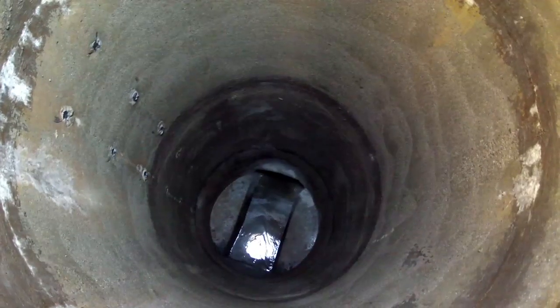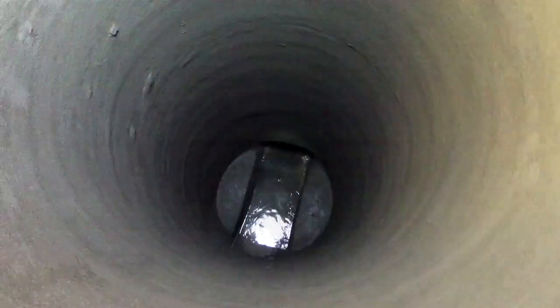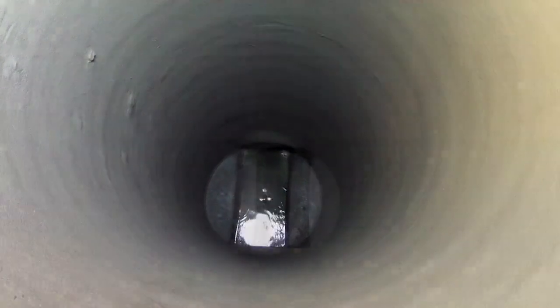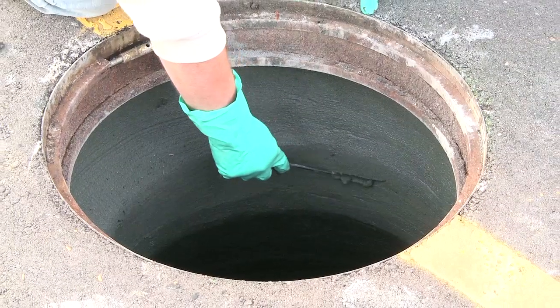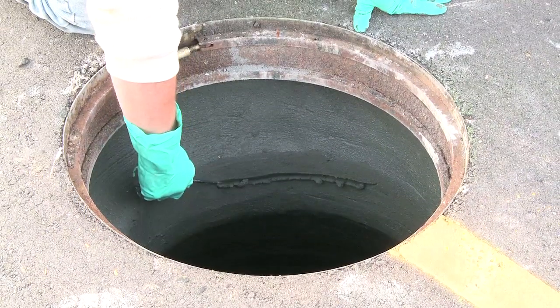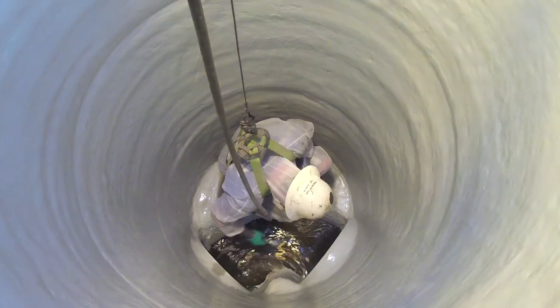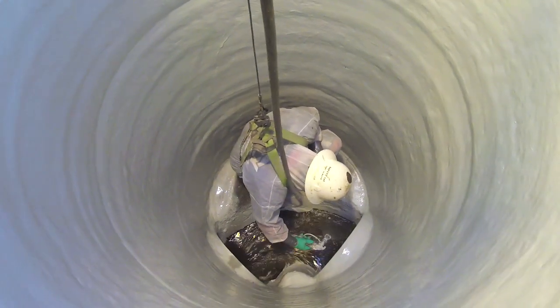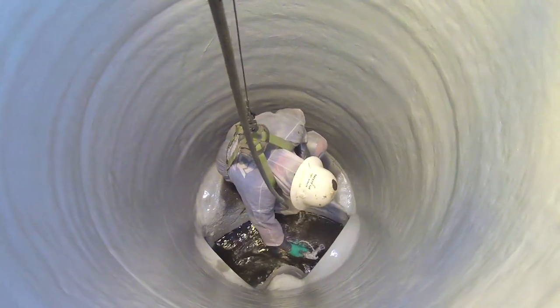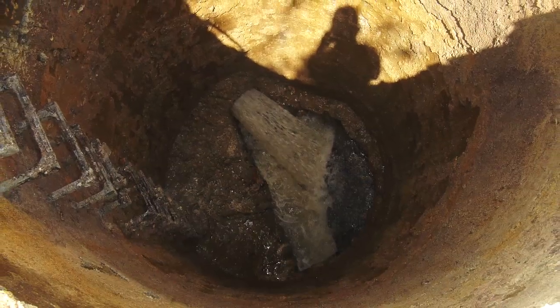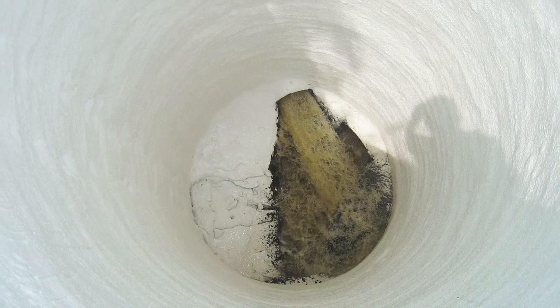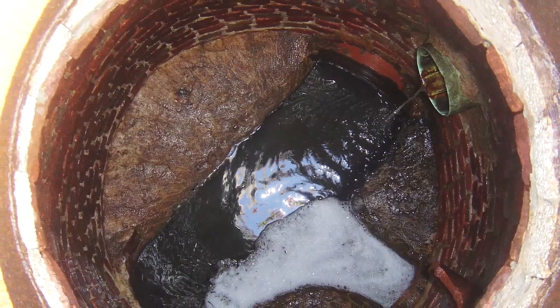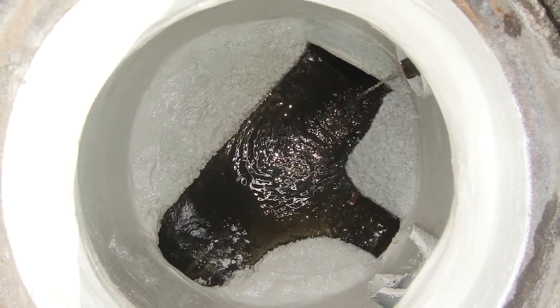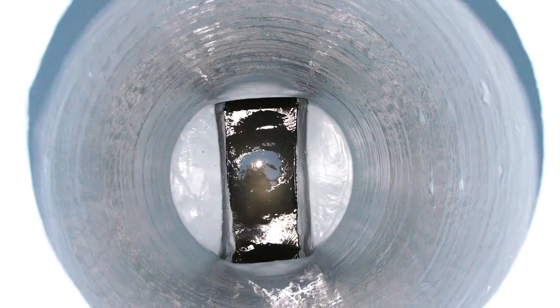The unique and essentially simultaneous application of both a restoration mortar and protective coating is the basis for the Mainstay composite liner. Because it is not necessary to wait for the mortar to cure prior to applying a protective coating, the structure can be placed back into service in less than one day. Structures that have been restored and protected with the Mainstay composite liner can provide over 50 years of structural integrity and resistance to corrosive sewer environments.